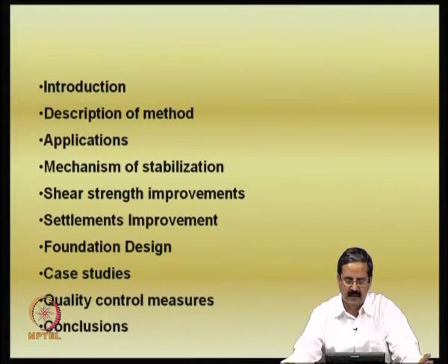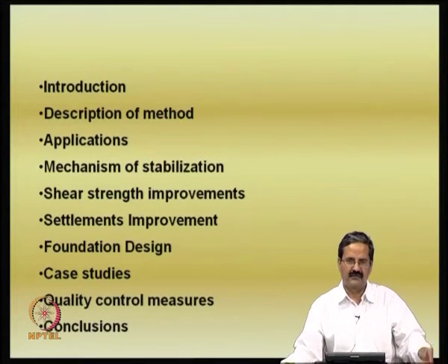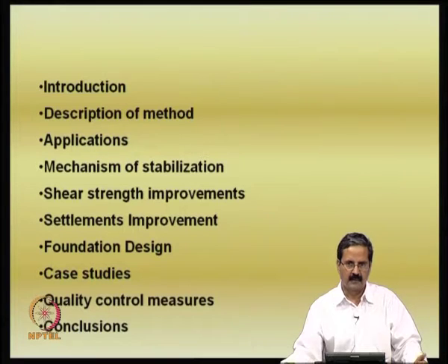Let me tell you the classical case of lime treatment itself. Lime treatment is very effective if there is no sulphate in the soil, but if sulphate is present in the same expansive soil, then it becomes worse. The expansive nature is judged in terms of the liquid limit of the soil or the free swell, and there are a number of tests one can do.